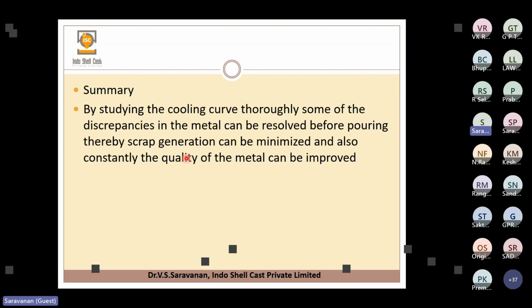We can improve the quality of the metal, and continuously we are working with the thermal analysis software and fixing the software parameters according to our process nature. Then the reliability of this particular software will be more. So we need to work with the software. We have to adjust the slope. The TL values, the T solidus, all those things, with the help of the formulas built into the software, we can slightly adjust the slope and then improve the values. Then the prediction will have good reliability.